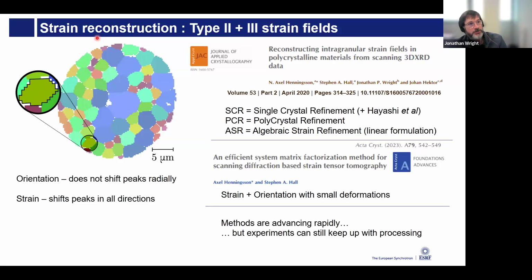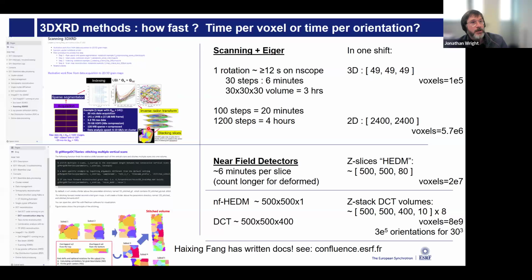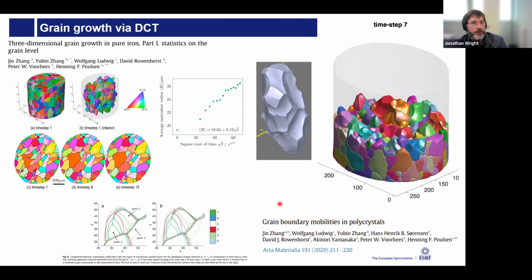So where things have changed, let's say in the last 5 years, is where we used to just do a strain mapping across a component. We now start to do a strain mapping from grain to grain and a strain mapping inside of the individual grains to cover all these different length scales. So I won't say very much about how long it takes to collect data. Suffice to say that it depends a lot on your sample and how you do the scans. But reconstruction of the data is usually a much bigger problem than collecting it. And so there's big progress for us that Haixing Fang has written up nice documentation to make those reconstructions go faster.